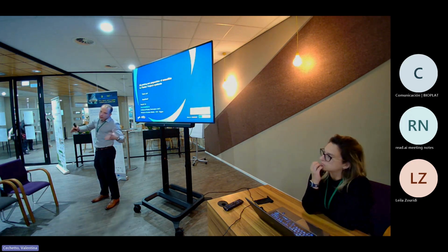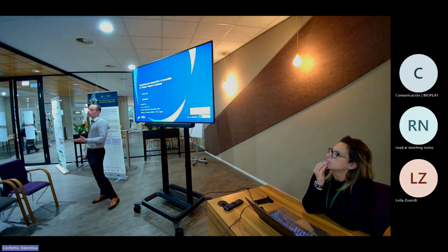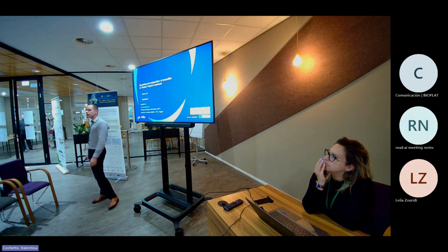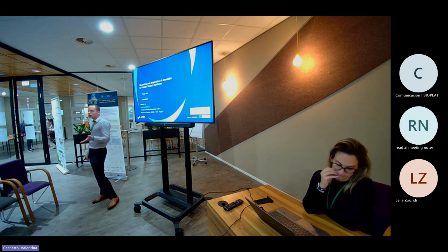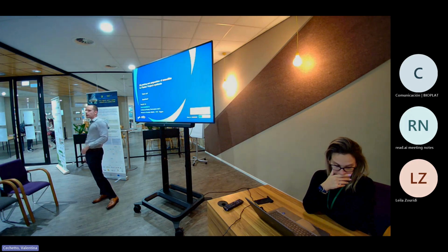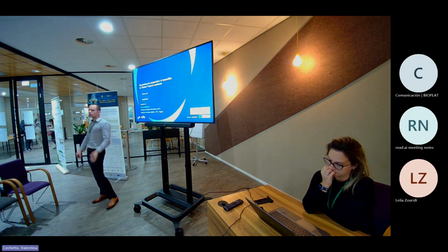But for really bulk products, it can be very interesting, as BASF is also building a pilot plant. For very cheap reactions, I think sulfuric acid production, they're currently using a 3D printed catalyst, and it's economically viable. But of course, the feature size is then very important for the throughput. I think with that, they use let's say 800 micron to 1 millimeter feature size, and then you can get real productivity out. But for small features, parallelization is very important, and that's something that we are still actively looking at. So thank you.